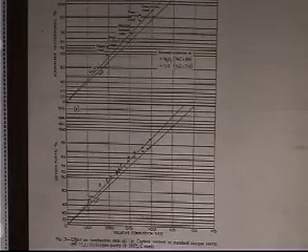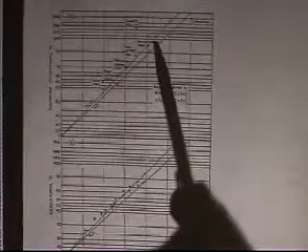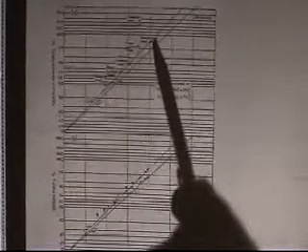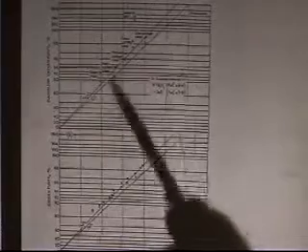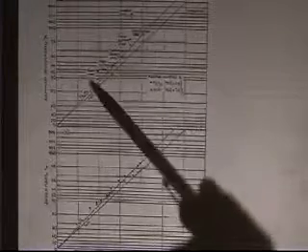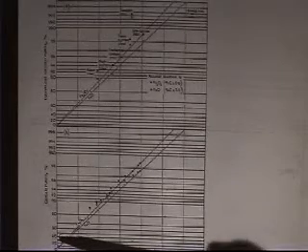You're burning the iron, and iron oxide is a liquid condensed phase, but steel is a mixture of not just iron, but iron and carbon. And if you burn carbon, you're going to get CO or CO2, mostly CO. And CO is not a condensed phase. So in fact, you would create your own boundary layer with carbon monoxide gas. The oxygen condenses to form FeO, but some of the oxygen doesn't condense, it forms carbon monoxide, and you have to blow that away. What this shows is the higher the carbon content of the steel, which means coming down this direction, the slower the relative combustion rate.